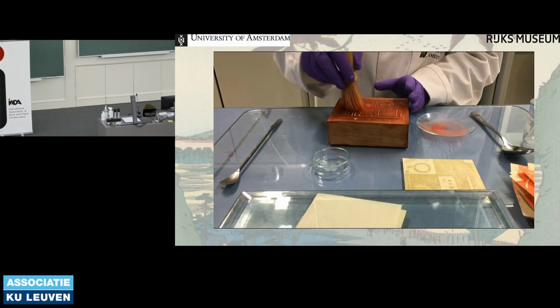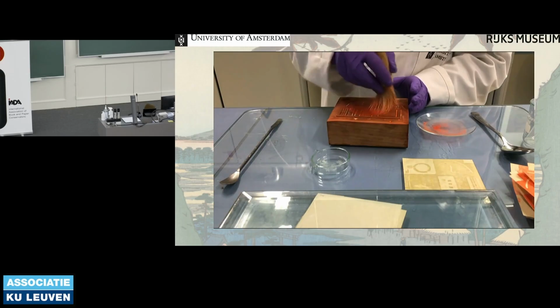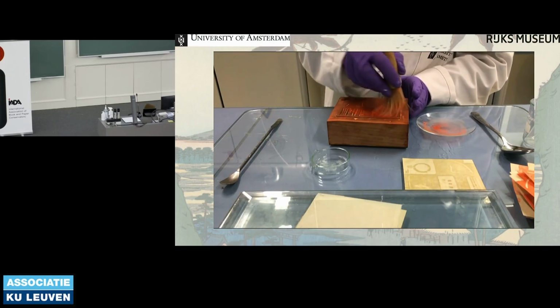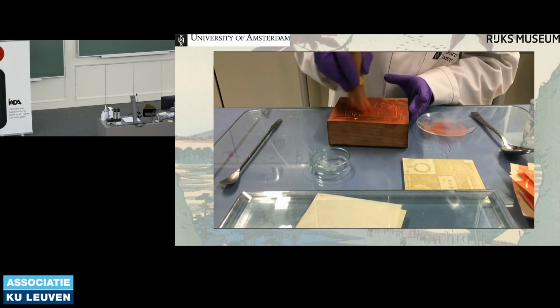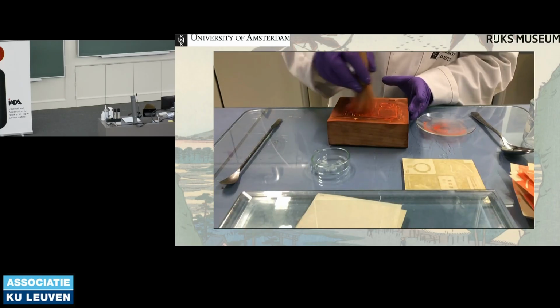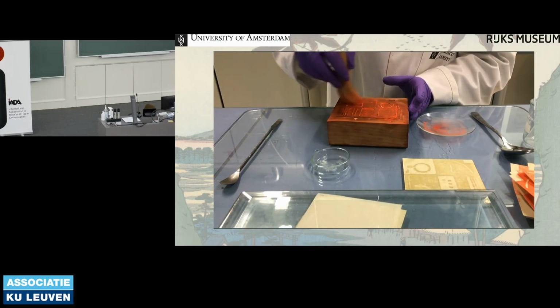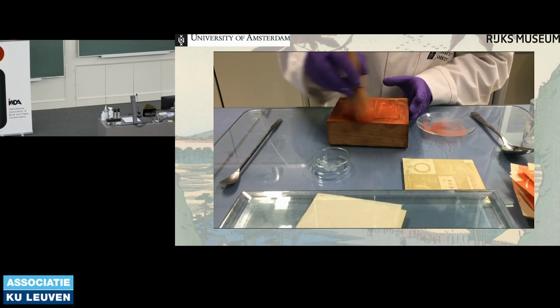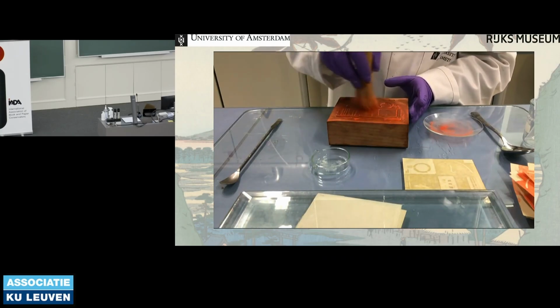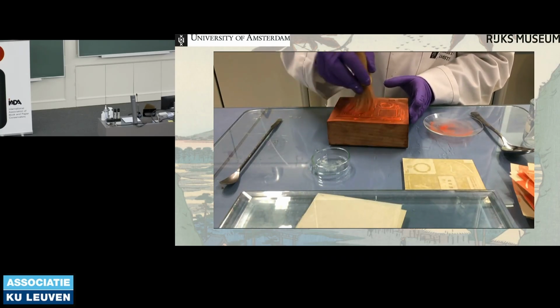Yeah, and you mix the binding agent and the pigment directly on the block. From there, you mix it in circular motions to make sure that it's as even as possible, and you just really mix it together to make sure that there's no large pools of pigment. Once that's done, you take the paper.